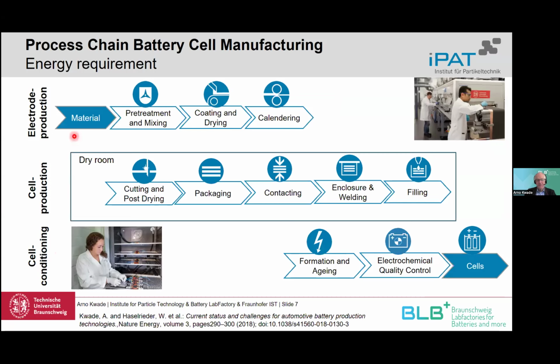You see that we have the raw materials, and they first have to be maybe pre-treated, but at least dry and for sure wet mixed. Then they are coated on a substrate, what you have just seen in the figure. It's made of aluminum on the cathode side, copper on the anode side. And then we have to dry the slurry in a state-of-the-art process. Then they are calendered. Calendered means they are pressed down to a certain porosity. And then we have to transfer them into the dry room because the electrolyte is very sensitive to moisture. So the electrodes have to be dried, and then we can package them.